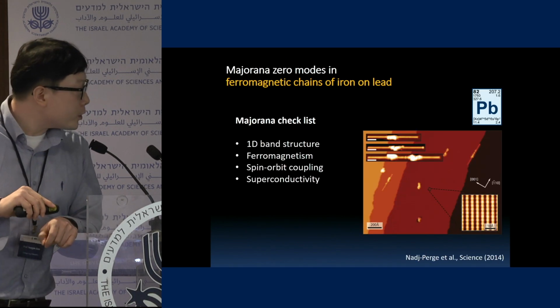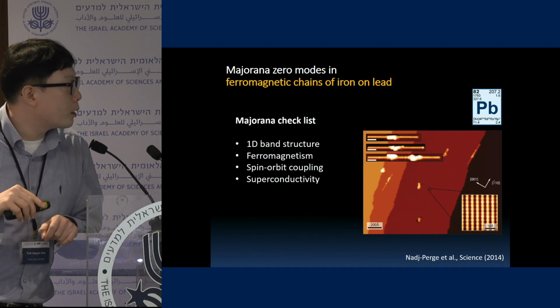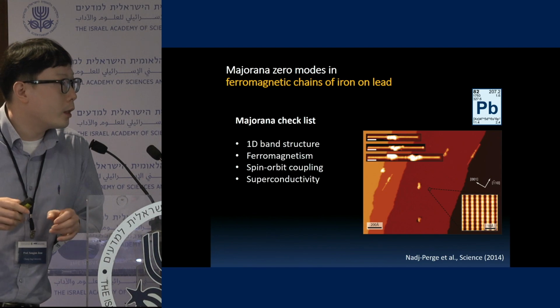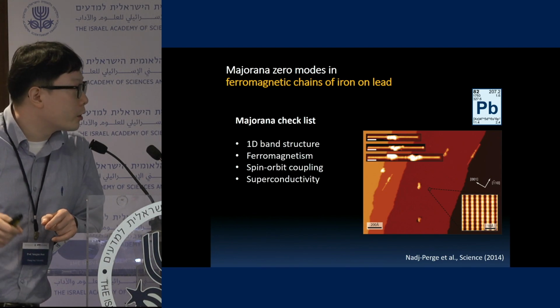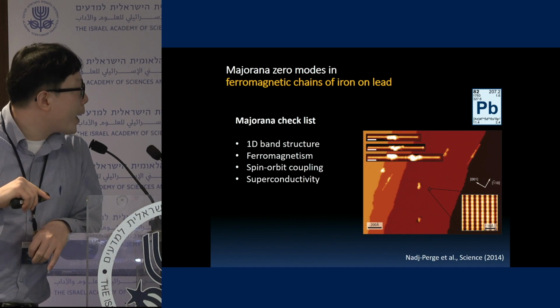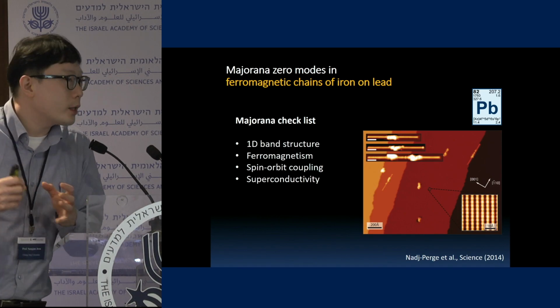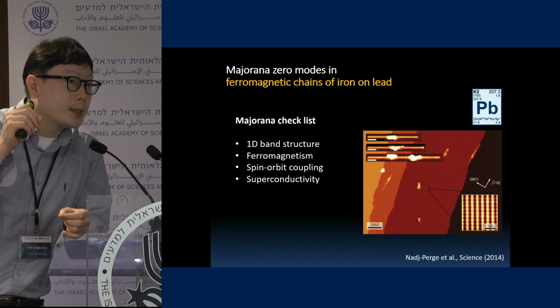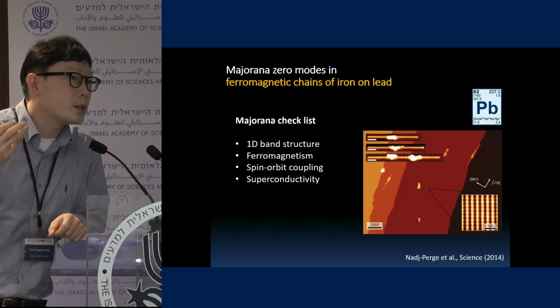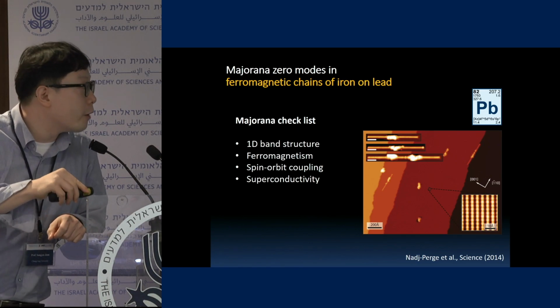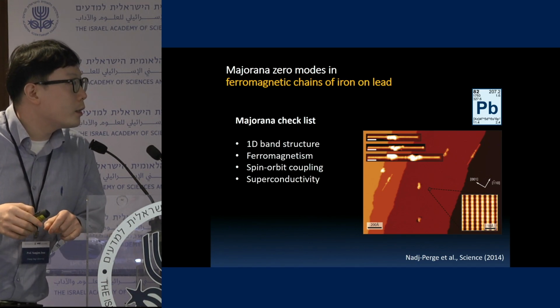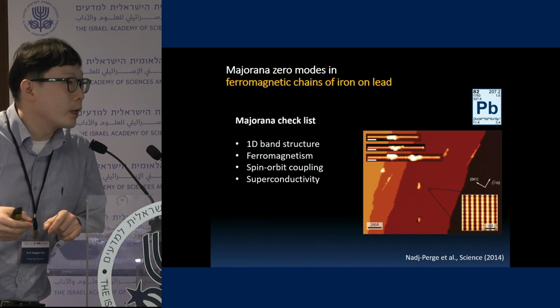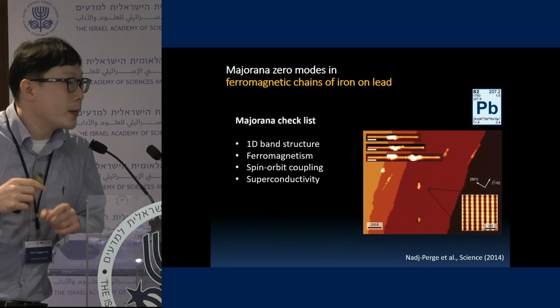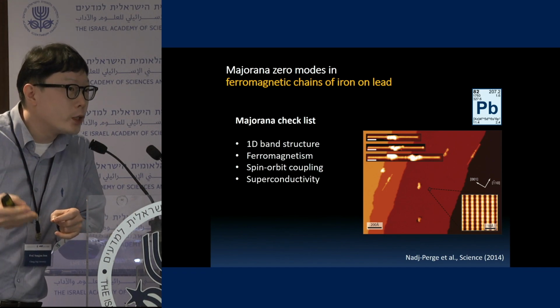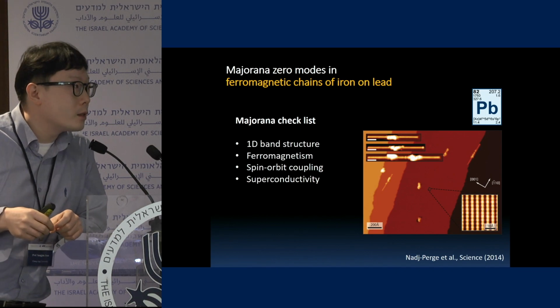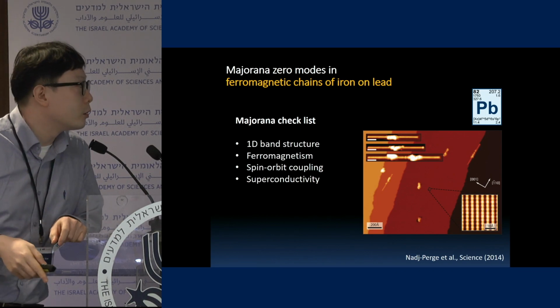Okay. As I mentioned, we chose a lead substrate, which is a single-element superconductor with a relatively high critical temperature. And then we chose iron as the magnetic atoms. Actually, at the beginning, we tried to manipulate single atoms to make chain structures, but it turned out to be very hard to manipulate them on lead substrates. And then we decided to use a self-assembled method to get wire structures. Basically, you evaporate the atoms, and using some heat treatment, they find some minimum energies, and then they make wire structures on the lead substrate.